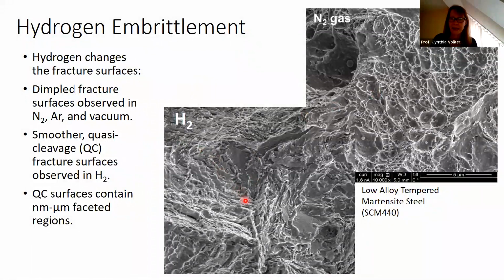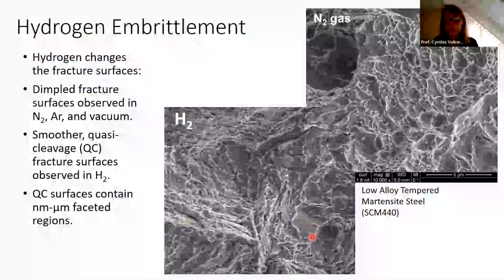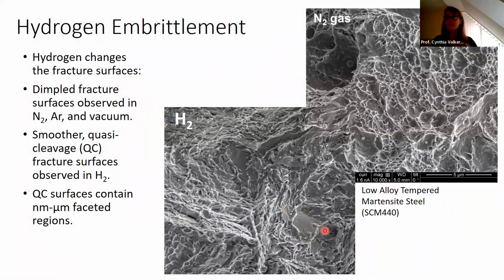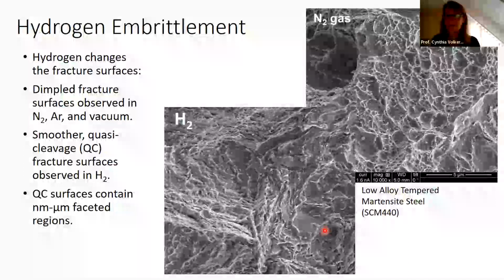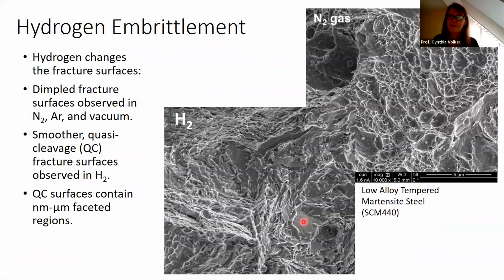Now, if we look at the hydrogen case, it actually looks quite different. Here you see there are almost no dimples. You might argue there are some dimples over here, but to a large extent, it's dimple-free, and what we have are small facets or small steps that are fairly flat. We also have some larger regions that are quite flat, and because macroscopically this looks flatter, as you saw in the previous micrograph, one talks about these surfaces as being quasi-cleavage surfaces. They're called cleavage because that typically refers to a split along a crystal plane, but it's called quasi because if one looks in, it's not a crystallographic plane that's the surface here, although some of these features do have crystallographic orientations. Some of the small facets do tend to have particular orientations, such as 100 facets, depending upon the material. So that's what one sees from the outside.